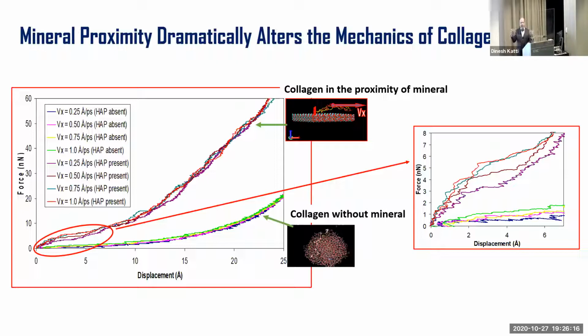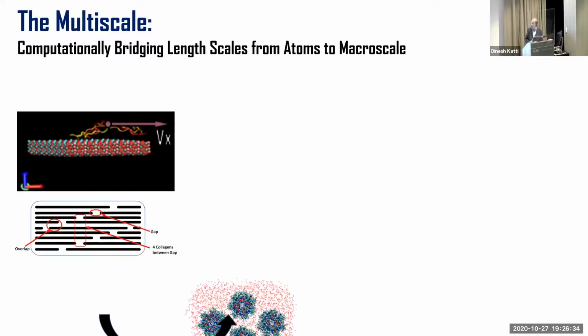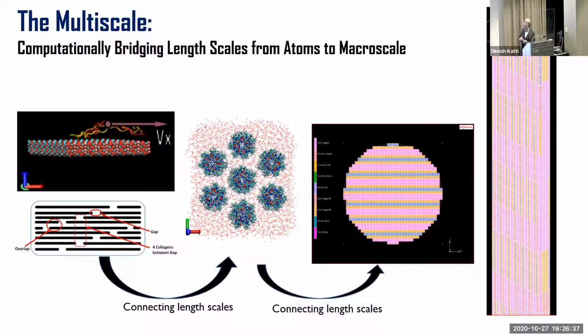This tells us that there's a very intimate relationship between the mineral and collagen, and that needs to be considered. But we wanted to see, what's the connection between what is happening at the molecular scale and the bone itself? And to do that, we did what's called multi-scale modeling. Basically, in multi-scale modeling, what we do is to bridge what happens at, in this case, the molecular scale to what is happening at the next scale, at the fibril scale, and then to the bone. So we build these bridges between these lengths. And we did that, and we found something very interesting.